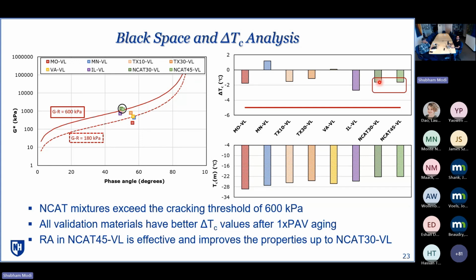So NCAT 30 mixture only had 30% RAP, whereas NCAT 45 mixture had 45% RAP in it with recycling agents. So here the recycling agent is working well, and it is neutralizing the effect of additional RAP we are considering in the mix. And it was true in the TCM property as well, again showing the effectiveness of the recycling agent in that mix.